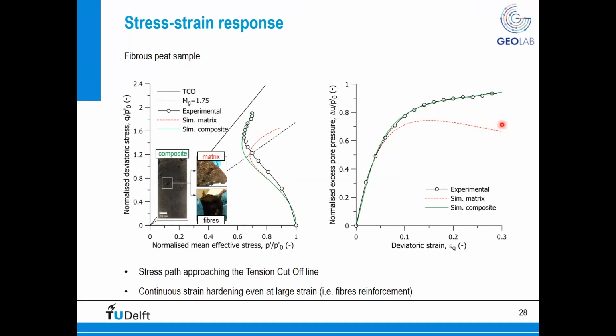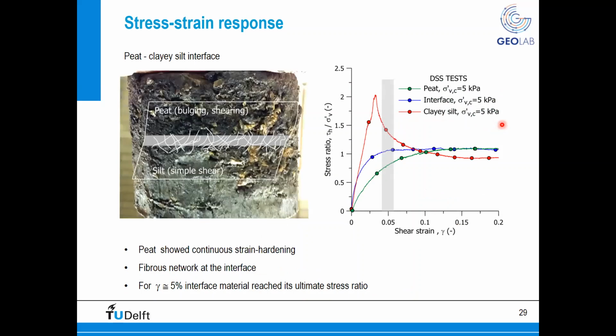Now, having an insight into how peat and the clayey silt behave is extremely important, because when you go back to the field, you need to imagine that these two materials, peat and silty clay, are not isolated, but are somehow communicating. And here on the left-hand side, you see an impression of an actual interface between a peat layer and a clayey silt layer. You see that we have a peat layer above, which is this dark material, and this peat layer is actually linked through a network of fibers, these yellowish fibers, with the clayey silt layer.